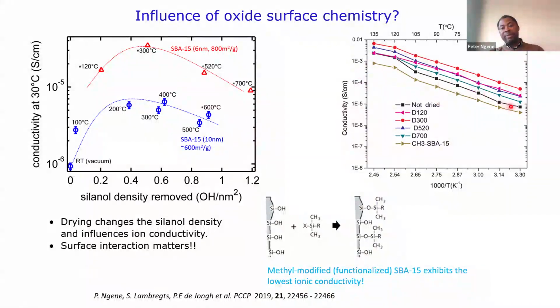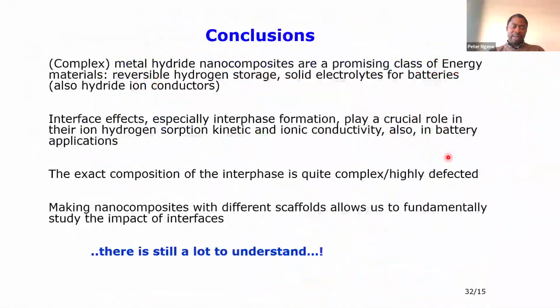I don't have time to explain why, but in fact this conductivity is a bit higher here because we are not able to completely remove all the silanol groups. There are what we call isolated silanol groups that cannot be reached to remove. So we think it is just these isolated silanol groups that are still responsible for the enhanced conductivity in this one, but it shows the lowest conductivity when we remove most of the silanol groups. So the interaction matters.